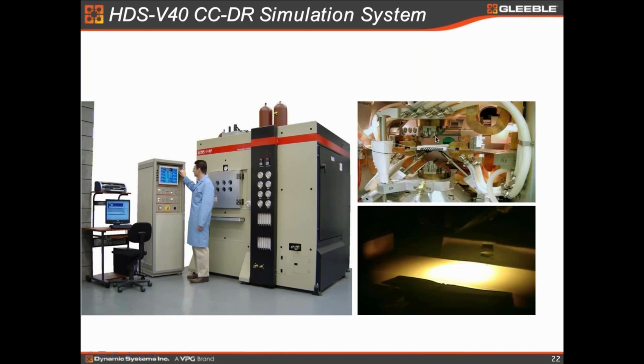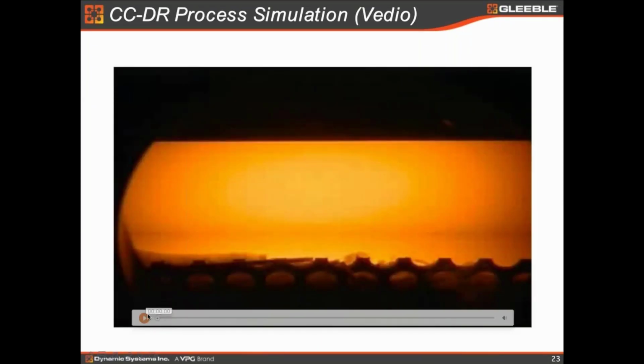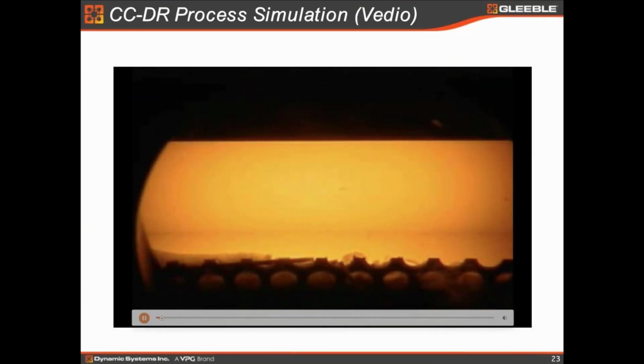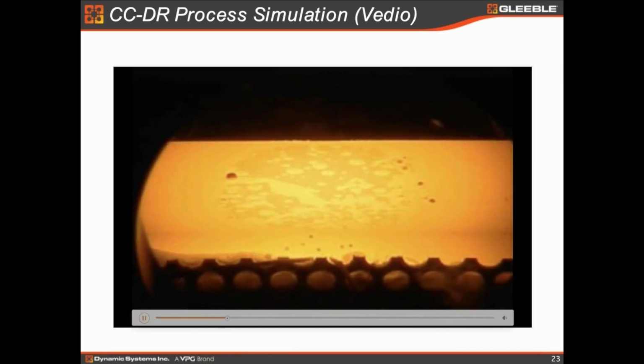Then, as I said, you use our crucible, which is really nice. You can bend it to the shape that you want to do the testing. Very economic, very cheap, I would say. Then you can heat it to whatever temperature you want. I'll show you a video to simulate the CCDR process in the Gleeble HDS V40. You see it's heating up a little bit slowly, but you will see a molten zone in the center. You can even see some gas popping up, and the center molten zone is generating gradually.